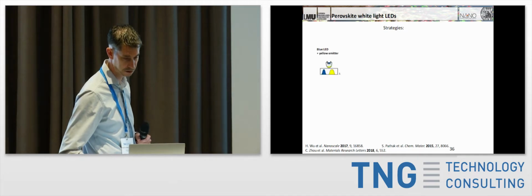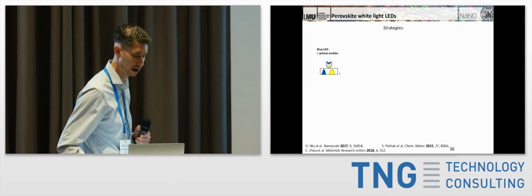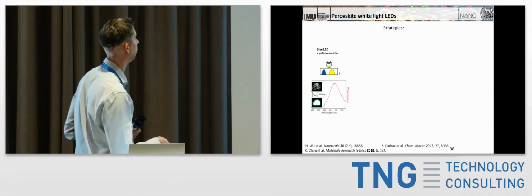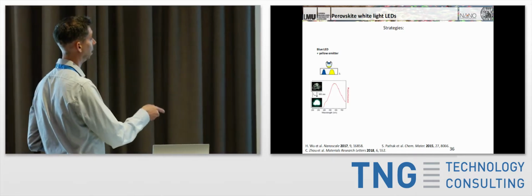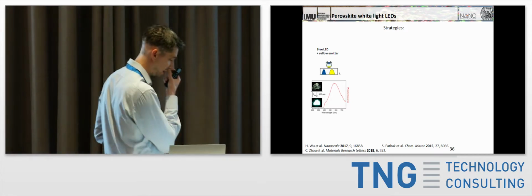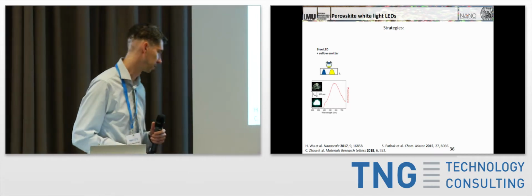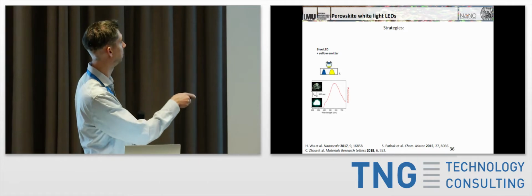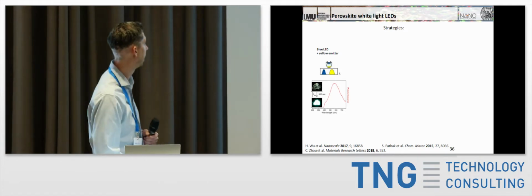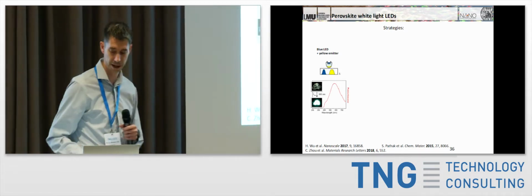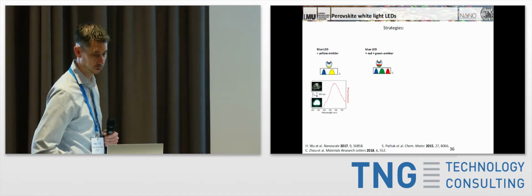Okay, so what about for perovskite LEDs? You have different strategies. Again, you can emulate the same strategy that we have so far, where you have a blue LED and you bring on a yellow emitter. This is an emitter where a process known as self-trapped excitons creates a very, very broad emission state in the yellow, and that produces essentially white light. So that's feasible with perovskites.